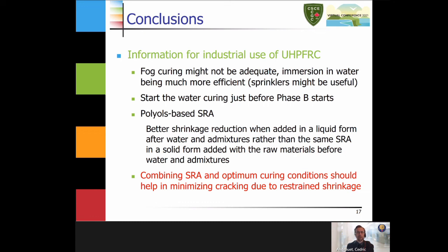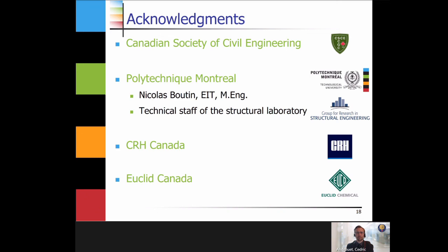And for the polyol-based shrinkage reducing admixtures, we've seen that we have a better shrinkage reduction when we add those materials in a liquid form after water and admixtures, rather than the same shrinkage reducing admixture in a solid form added with raw materials before water and admixtures. So finally, if we combine the reduction in shrinkage provided by the SRA and optimum curing conditions, then definitely it will help in minimizing the cracking due to restrained shrinkage.